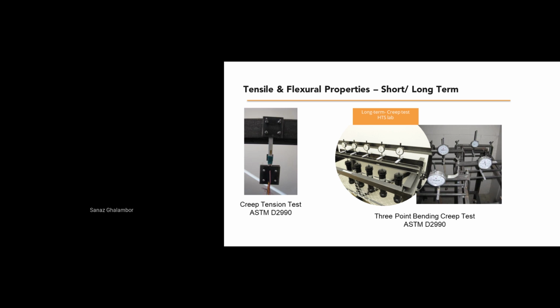I should go faster. So we have also done the tensile and flexural tests, short-term and long-term, to predict the strength of the material and dimensional changes under long-term loads, and the material's long-term performance extrapolated for 50 years, because we design our system for 50 years. And these are polymers, they go through creep. We want to make sure that our system can last for 50 years. So the numbers, the properties that we use to design the pipe should be the numbers after 50 years, not the numbers for the short-term testing.